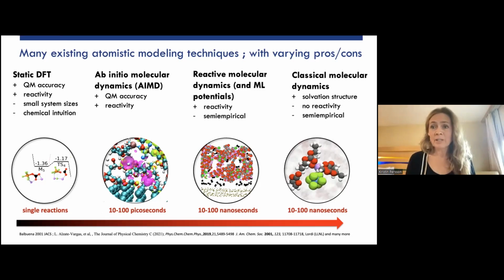Ab initio molecular dynamics exposes a little bit more: let's just put these molecules in a box and see what happens. So there's slightly less bias from the modeler themselves. But on the other hand, the accessible lifetimes today of those simulations are up to about 100 picoseconds, and that's really not enough to truly examine the configurational landscape and reactivity of a true electrolyte. To give you a sense, just one solvent molecule exchange on a working ion is on the order of 10 nanoseconds. So we're not really there. It's just going to look at the local configuration that you put together in your box.